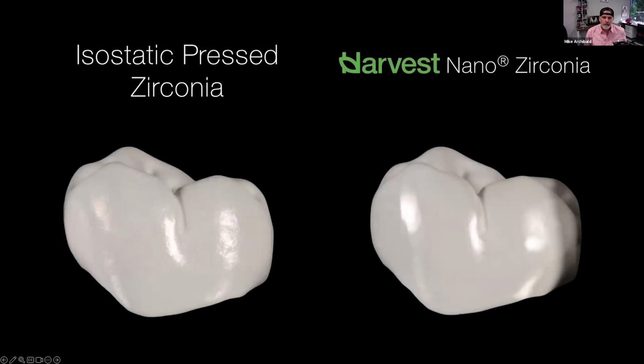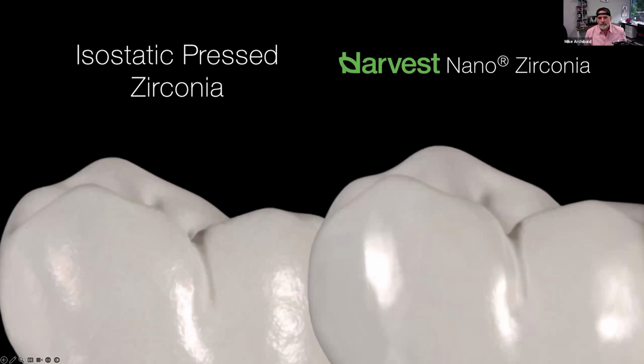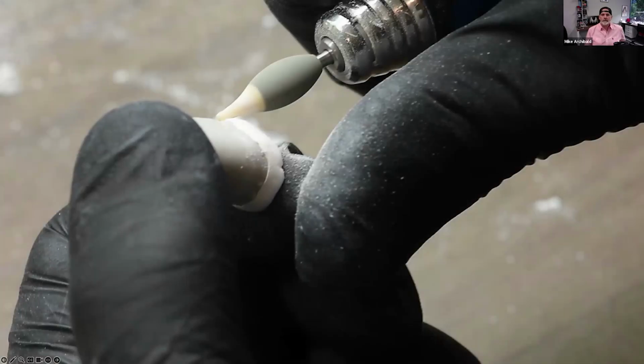I wanted to highlight this: if you were to take a regular isostatic press zirconia and polish it to as high of a shine as you can get it to, you're going to see some level of porosity. Whereas if you take the nano zirconia, that surface finish is going to be a luster, high shine, very little to no porosity. And if you zoom in here, you can really see the surface difference of each of these surfaces. That is achieved through the small particle, high density process of how we make the Harvest nano zirconia.